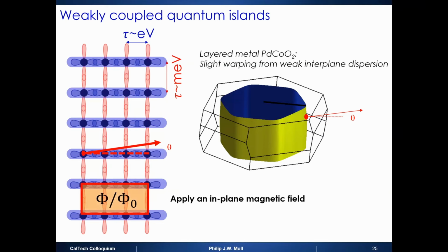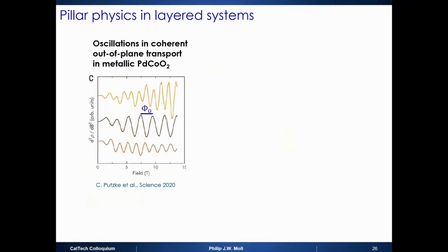For example, you can apply an in-plane magnetic field. So you put some field in between these planes, and then you see an Aharonov-Bohm-like effect of interference when these wave packets move into the next layer. It will count how many single particle flux quanta are stuck in between these atomic planes. And if you do this, you see fantastic magnetoresistance oscillations. So this is the second derivative of the magnetoresistance along this thing as a function of field. You see these field linear oscillations, they're exactly single particle flux quanta stuck in a box.